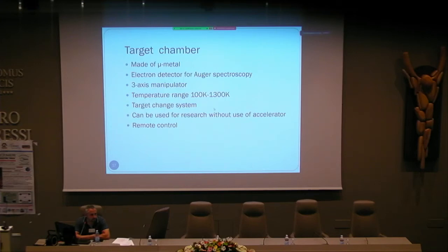From the experimental point of view, of course, the problem is that if you cool down the targets you have some water at the surface, but if you bombard the targets, you can increase the temperature of this first layer. Another point is that you have sputtering. The lower the energy of the projectile, the stronger the sputtering. So at very low energies, you can clean your target yourself. It's a very nice effect, and we use it for our purposes.